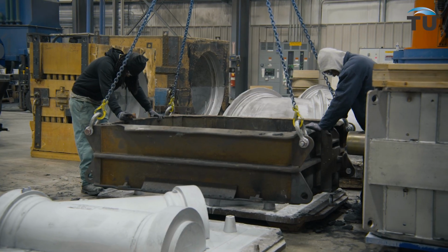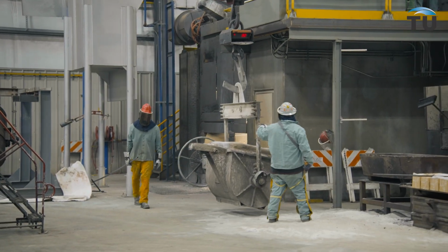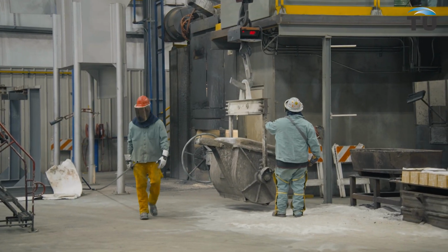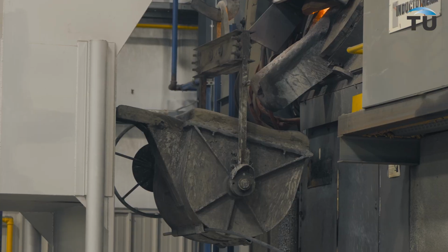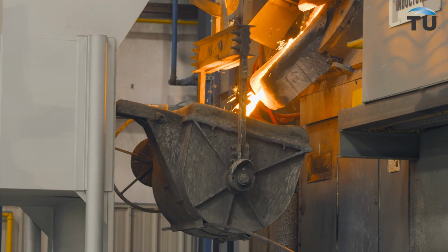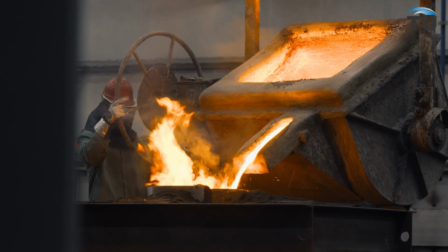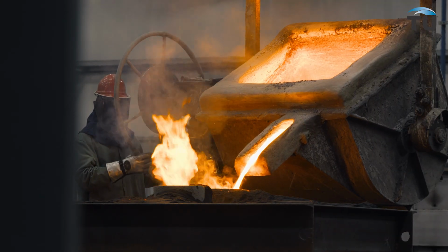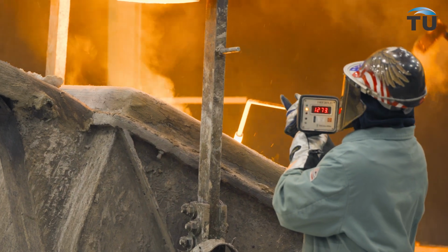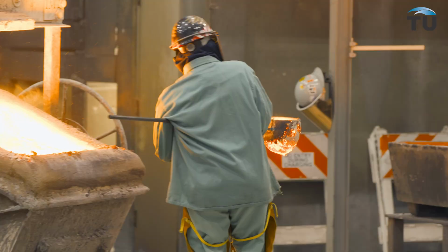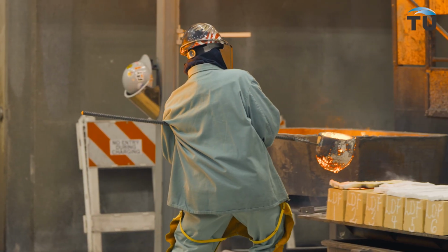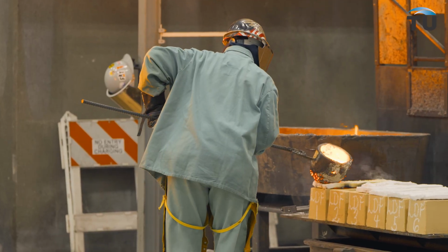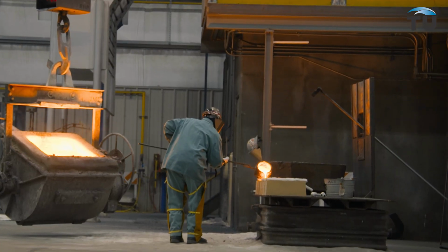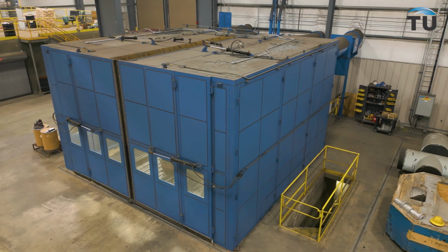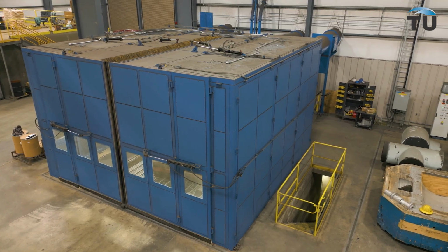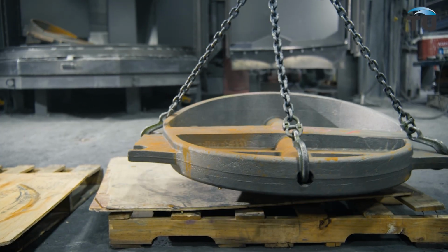When flasks are assembled, a ladle, charged with the correct amounts of magnesium and silicon, is placed underneath the induction furnace, and pouring occurs. The melted ductile iron is then poured from the ladle into the mold flasks to produce the castings. An iron chemistry coupon, as well as ductile iron tensile strength samples, are collected for quality assurance from the iron. A shakeout process is used to separate the sand from the casting. Castings then head to the shot blast.